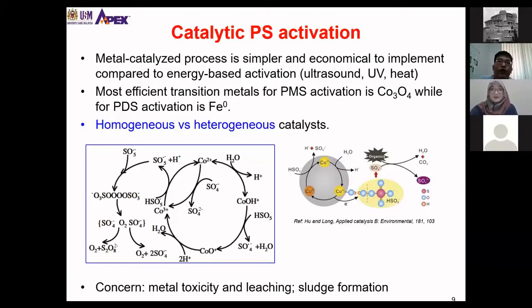Okay. Homogeneous means that you are using the dissolved catalyst, which means that if, let's say you are doing PMS activation, you want to use cobalt, right? You use cobalt salt, you add it into the reaction vessel, and then this cobalt will dissolve in the water and it acts as a catalyst. On the other hand, heterogeneous catalyst means that we are using the solid catalyst itself, okay? Which means the catalyst will not dissolve in water. You put it inside, it will react as a catalyst, and then after that, you can recover the catalyst. Okay? There are many ways where you can recover the catalyst. You can design the reaction vessel to have a filter to filter off the catalyst.